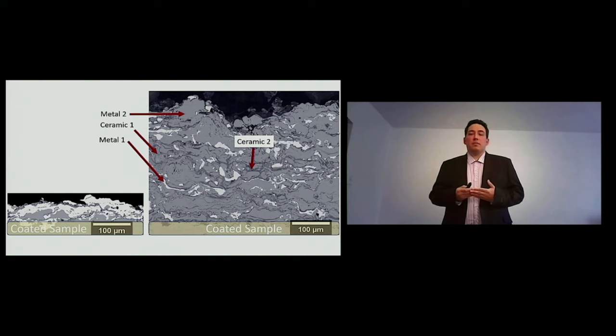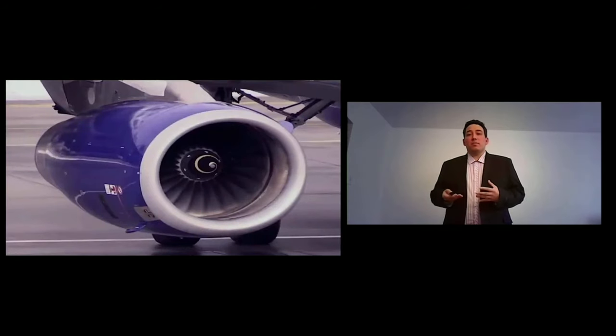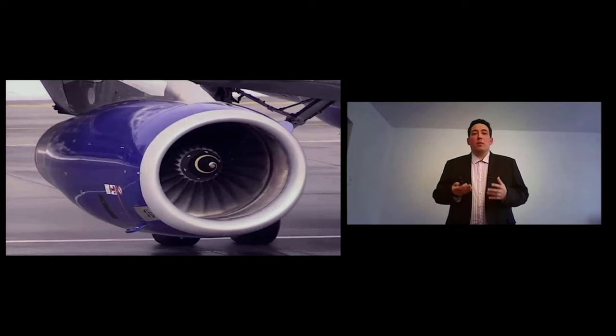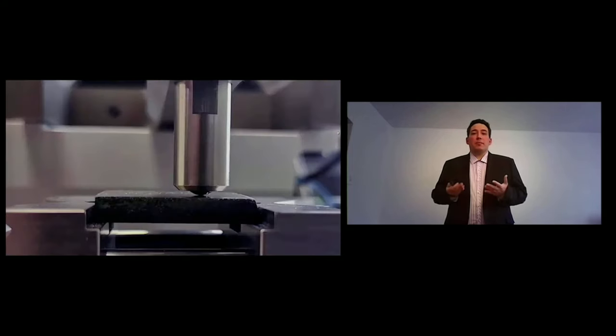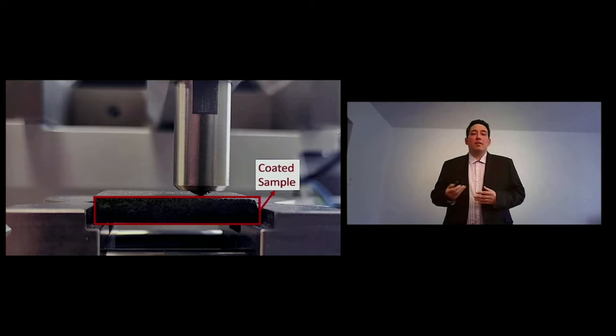Okay, but now we have a suitable coating, a good coating. How do we test it? Well, ideally, what we would do is put it on the turbine or on the engine, put it to run, and then see how it goes. However, this is really not possible under the conditions that we have. So what we need to do is try to replicate those conditions in a small scale experiment. We do that by using a tribometer, just like the one you see in the image. What you see here in the bottom part is our coated sample and the counterface on top.